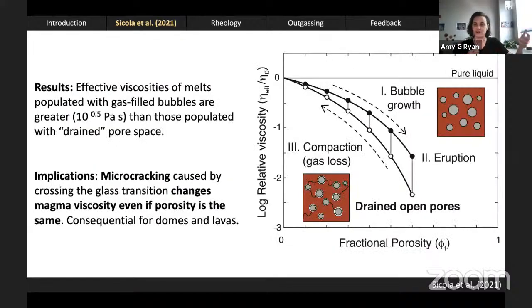One has a higher viscosity because it's populated with gas-filled bubbles. It is a closed cell material. And the other one, while masquerading as closed cell, is actually populated with drained pores and was open cell at one point. This is consequential because it means that microcracking, whether as a result of cooling across the glass transition or by being strained faster than the material can relax, again crossing the glass transition, changes magma viscosity even if the porosity of the material is exactly the same.